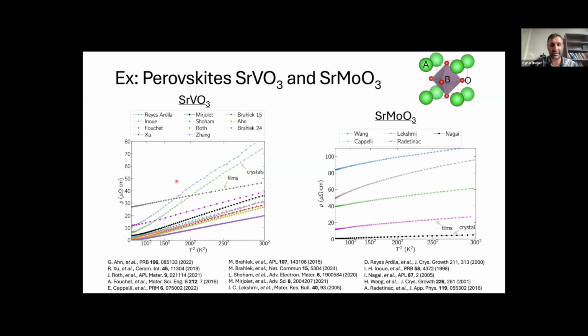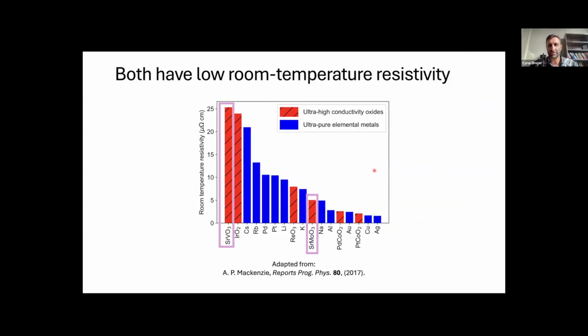And so there's a lot to unpack here with the experimental agreement and disagreement that I won't go into too many details. But I just want to say that these materials show this T squared behavior, and I definitely wouldn't consider these strongly correlated materials. In fact, they are some of the highest conductivity metals that are known. Here I'm plotting room temperature resistivity for basically the highest conductivity metals measured. And you can see especially strontium molybdate is very high conductivity, similar to alkali metals, lower even than some elemental transition metals. And strontium vanadate also has a quite reasonable room temperature resistivity.